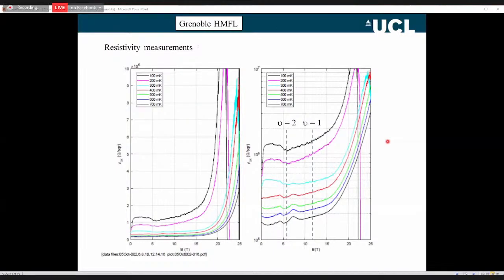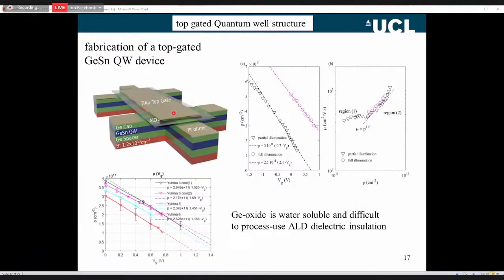So I'll just quickly show you. If you look at the structure here, what we do is we pass a current down the Hall bar, a small current, usually 1 nanoamp, and we measure the voltage drop along the Hall bar on other contacts, and that gives us a resistivity. And then we apply a perpendicular magnetic field. The field is perpendicular to the device. So we can measure the Hall effect. The Hall effect would be across the Hall bar, and the resistivity, our RXX, would be along the Hall bar. I didn't show any Hall effect data from Grenoble, but we have the data also. It's a standard resistivity measurement.